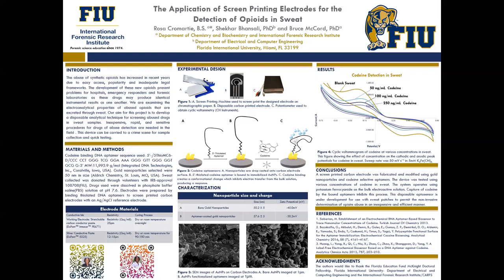So in conclusion, this presentation shows the fabrication and modification of the screen printed carbon electrode using gold nanoparticles and selective aptamers. The system operates using potassium ferrocyanide as its bulk electroactive solution. And we were able to test this device using various concentrations of codeine that was in sweat.